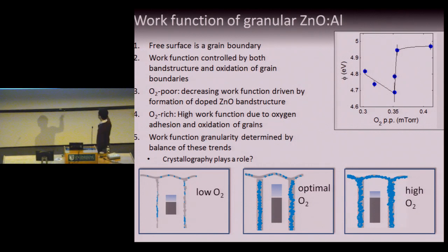As you go towards optimal material, you have an increase in the density of oxygen defects segregated along the grain boundaries. And for well understood reasons, now, well, it's all obvious in hindsight, these grain boundaries should appear as high work function elements. So now you're starting to develop electronic granularity as you scan across this material, and you're sensitive to the oxidation state on grain boundaries as opposed to over grains.